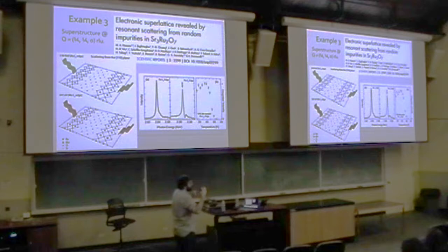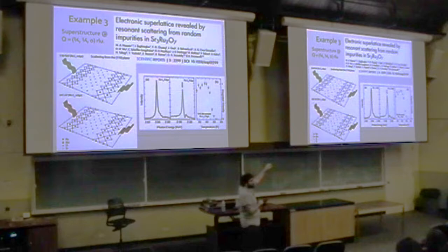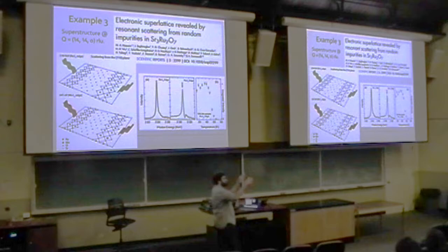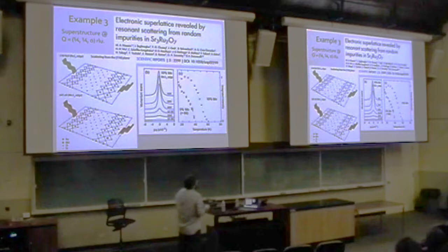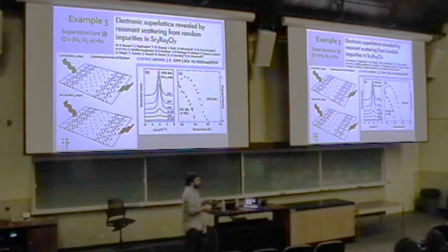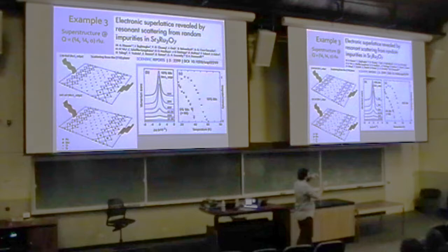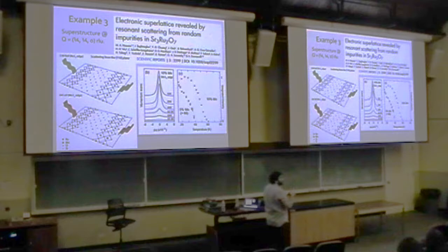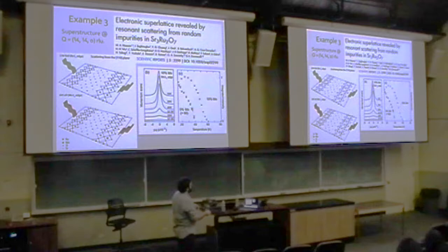But now the idea is, what happens if I remove some of the ruthenium and substitute some manganese, and then decide to use the manganese edge instead? Okay, sort of use the manganese as like an infiltrated probe of the environment where the ruthenium oxide is. And in that case, if you do that substitution, in this paper they measured 10% manganese, you can see that at 60 Kelvin, well, they detect a peak at low temperature. And it has the same temperature dependence, more or less, as the measurement from the ruthenium. And at 10%, it's okay, because at 10%, the average distance between the different manganese is going to be comparable to the correlation lengths that quickly develop inside the ordered state, so you get a coinciding transition temperature here.